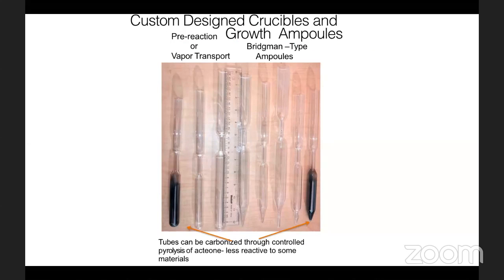So this is the quartz crucible, which one can use for normal chalcogenide materials. Sometimes if you use metals, the metal can react with quartz, and it will loosen the hardness of the quartz. So people use a pyrolytic coating on the quartz tube, and it will protect the quartz tubes. So these are different designs for different crystal growth purposes, particularly Bridgman growth.